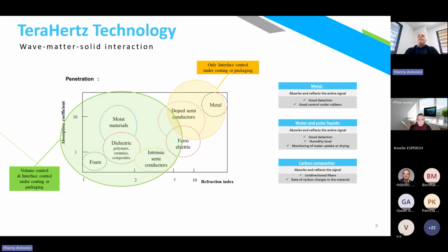The main principle of this wave in terms of wave-matter solid interaction is that all materials are classified in this graph. Some materials are quite absorbent, so of course we won't be able to penetrate them. For instance, metal is quite absorbent, and at the same time metal is also quite reflective. That is why we cannot penetrate metal as a conductive material. On the contrary, polymer, ceramic, composite, foam, we can penetrate easily. And one more thing is important to know about such a wave: water and polar liquids are quite absorbent. So if there is too much water inside the material, we won't be able to penetrate. On the contrary, a small quantity of water inside a material could be easily detected by our waves.